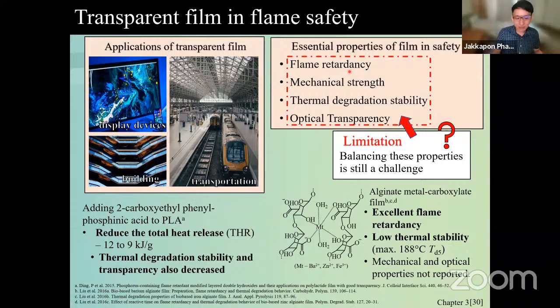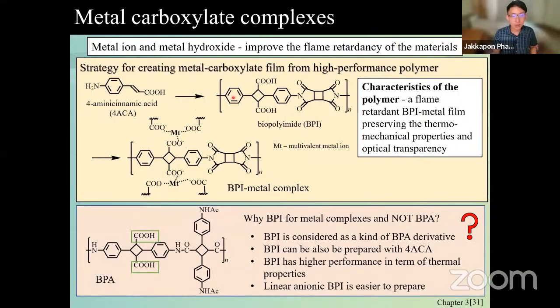We have some kind of metal alginate here, but it's not very flame retardant at all. Okay, we have the 2-carboxyethyl and the PLA2, but again, the heat release is quite good, but thermal degradation is very bad. So here, I'm going to try to use the glucose base again, ACA, to make biopolyimide. And because it has this carboxylic acid on each side, right? I'm going to make a complex of metal, okay? Scavenging to make it a BPI metal complex here, okay?